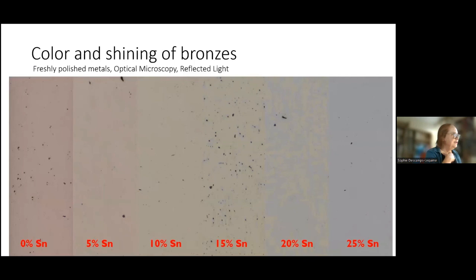And this, I think, is very important to understand what was the palette of bronzes. On the left, you have an unalloyed copper with no tin, and it's only pinkish. And then you have on the third line a 10% tin copper alloy, which was the color of most bronze. So the polychromy was very subtle, and the ancients really valued the brightness and brilliance of metal, but everything was very subtle.